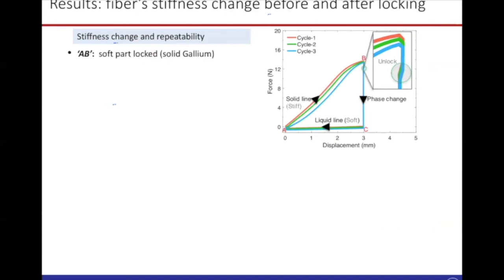To check the repeatability of stiffness change, we use this force displacement curve in a tensile testing machine. So you place your hybrid fiber in a tensile testing machine and you pull it to around 3 mm, and you record a large force when the gallium is in solid phase. It means the soft part is locked. And at point B, we switch on the power.